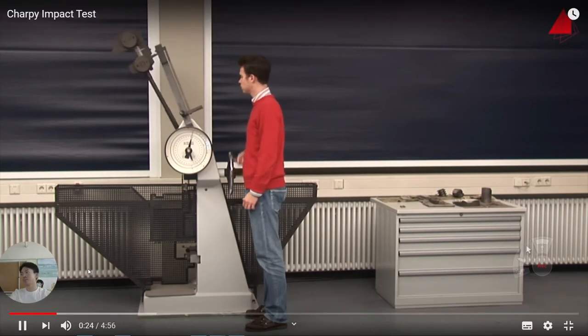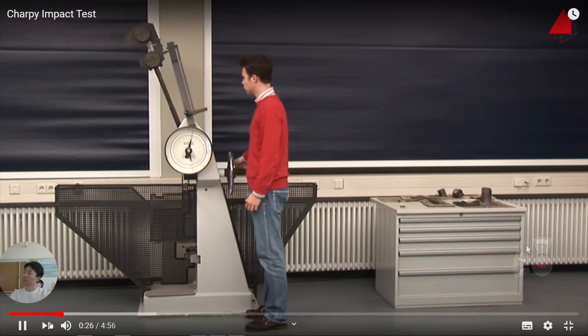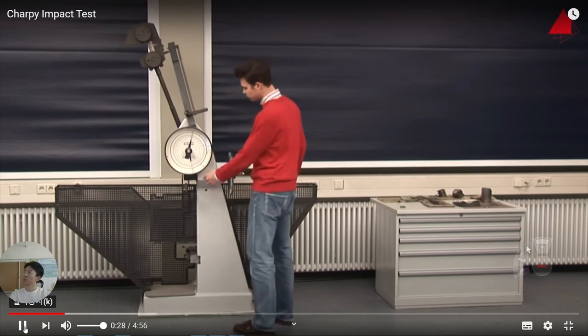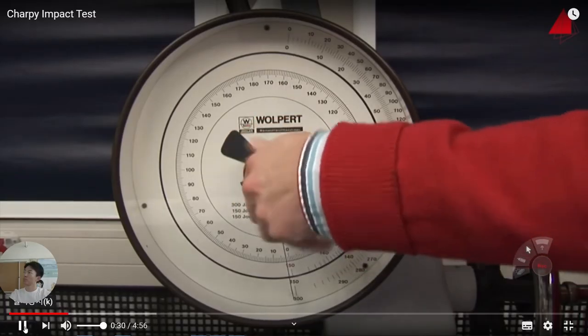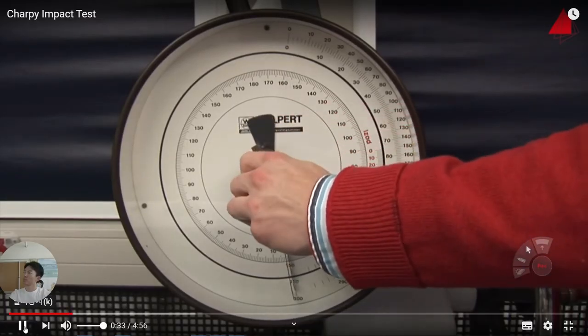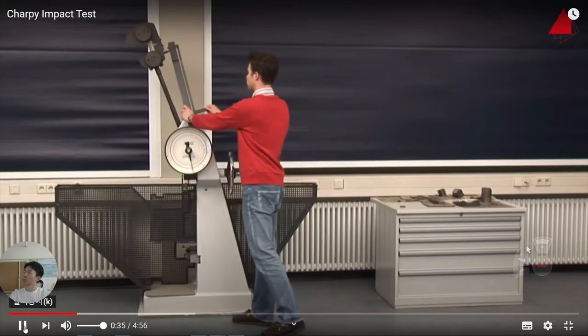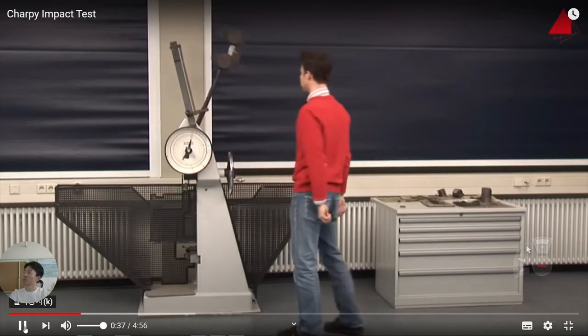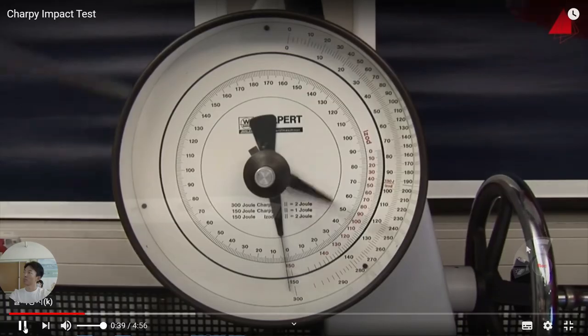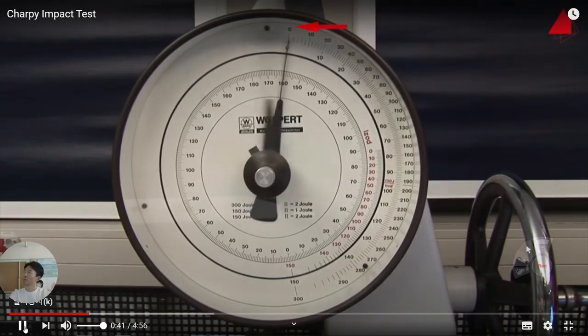Then the tester checks whether the testing machine has been adjusted accurately. In order to do this, he turns the drag indicator downwards and releases the pendulum without a test specimen. The drag indicator stops at position zero. This proves that the pendulum has the correct starting position and that the friction is correctly compensated.